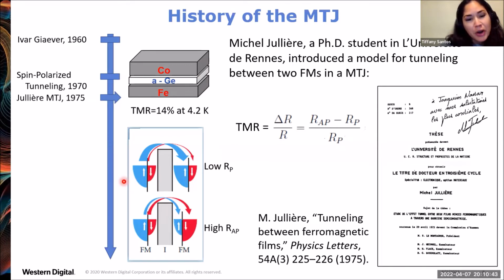So in ferromagnets, what's special about them is that due to the exchange interaction, you have asymmetry of the density of states. You have a majority of one spin orientation compared to the other. So when the two ferromagnetic electrodes have their magnetization oriented parallel to each other, you have a lot of spin up electrons in one electrode and a lot of empty spin up states in the other ferromagnet, and this results in a high tunnel current and correspondingly a low resistance state. When the two ferromagnets have their magnetization oriented anti-parallel to each other, there's a mismatch of the density of states of the two ferromagnets, and this results in a low tunnel current and correspondingly a high resistance state. And the tunnel magnetoresistance ratio is the difference between the anti-parallel resistance and the parallel resistance over the parallel resistance state.